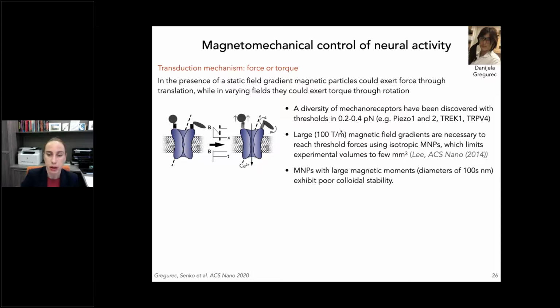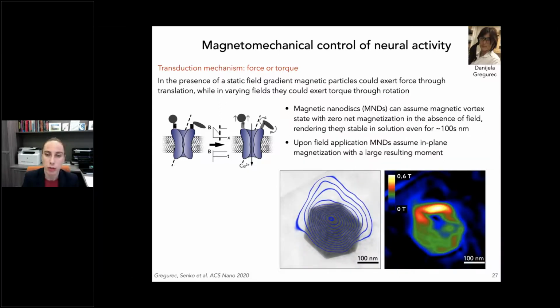This problem has been addressed by a talented former postdoc who is now a professor in Dresden, Dr. Daniela Gregurec, who has considered a new class of particles, drawing inspiration from magnetic memory, where people have been studying a magnetic state called the vortex, where all the atomic spins within iron oxide or other magnetic materials can line up in a circular arrangement, resulting in a zero net magnetization. We can measure this state in disc-shaped particles using electron holography, demonstrating to ourselves indeed that we see vortices. And we can see that the magnetic field around these particles is also quite negligible, which means they do not have external magnetization, and they're not going to stick to each other in solution.